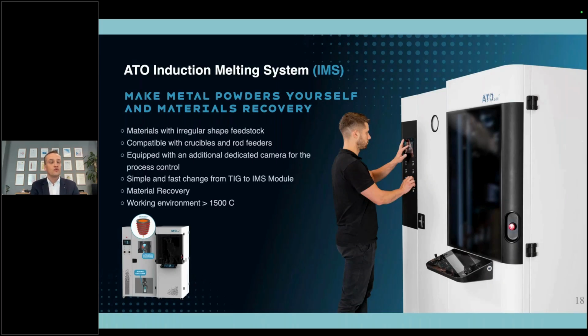So whenever you need to recycle some scraps after the 3D metal printing process, maybe supports or CNC scraps, or even shorter or longer bars, you can use the induction melting system, which is much more gentle for the material in comparison to the plasma source, for example. So whenever you need to work with lower melting point elements like tin, lead, magnesium, the induction melting system seems to be the best choice for you. It can work with materials with melting points of more than 1500 degrees, and it can turn your scraps or even another powder into a perfectly spherical powder with a very narrow particle size distribution.